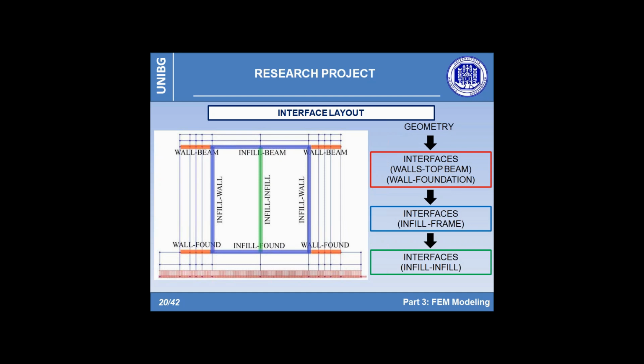In this case, the aim was to replicate the formation of the sliding vertical surface due to the interaction of the wire mesh. In fact, during the test, increasing the external displacement, the pre-existent shrinkage crack along this direction became wider, causing the 2 halves to behave as 2 distinct parts, almost completely independent and connected each one only to the closer shear wall.